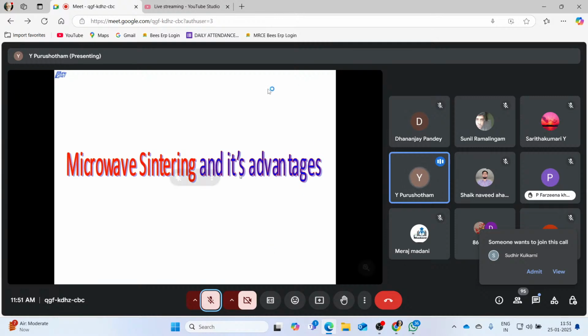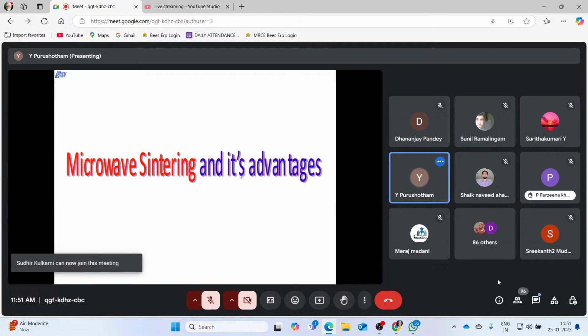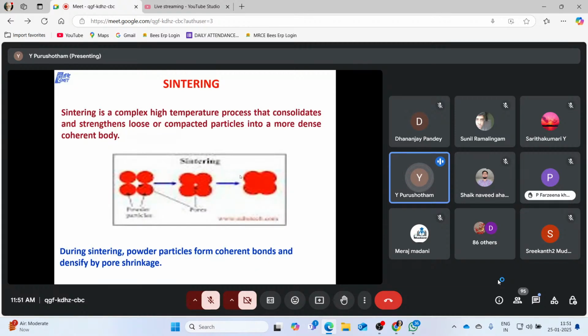So next, what I want to discuss with you is microwave sintering and its advantages. Because in induction heating, I just briefly mentioned microwave sintering. Sintering is a complex high temperature process that consolidates and strengthens loose or compacted particles into a more dense, coherent body. So what is happening during sintering? Powder particles form coherent bonds and densify by pore shrinkage. If you want to make a dense material, you have to sinter, whether it is resistive heating, induction heating or microwave sintering, but sintering is only to densify. The pores, whatever is there, will shrink. Shrinkage takes place during the sintering process.